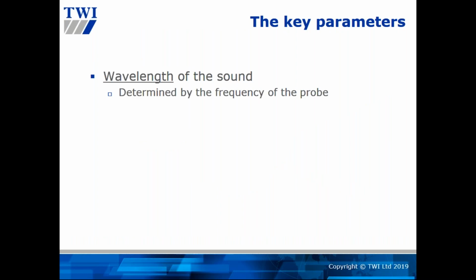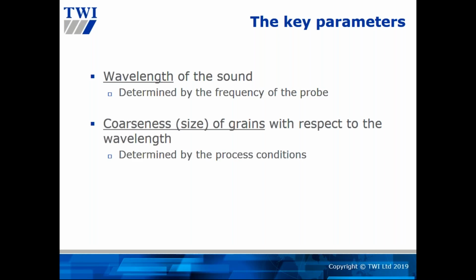So, as I said, a pragmatic approach will require an understanding of the key parameters. And one of them, as I illustrated earlier, is the wavelength. Essentially, if you can make the wavelength larger with respect to the grains, whether that be the carbon steel grains or the grains of the cladding, then you can improve the efficiency of the sound propagation. Again, that depends on the coarseness of the grains, and the coarseness of the grains themselves depends on the process. So if it's a manual metal arc deposition, for instance, it can often lead to a larger grain growth than an automated TIG process.